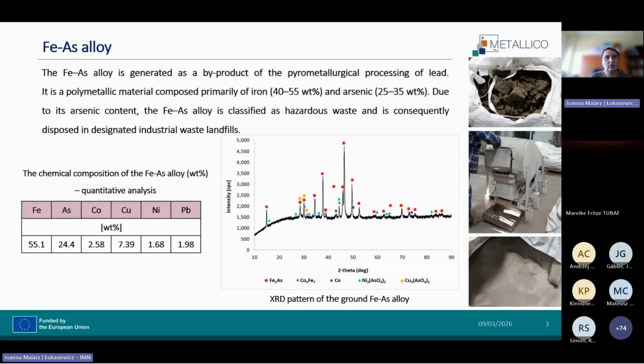The iron arsenic alloy is a polymetallic material composed mainly of iron and arsenic. A typical alloy contains about 40 to 55% iron and 25 to 35% arsenic. Because of its high arsenic content, this alloy is classified as hazardous waste and is usually deposited in designated industrial landfills.